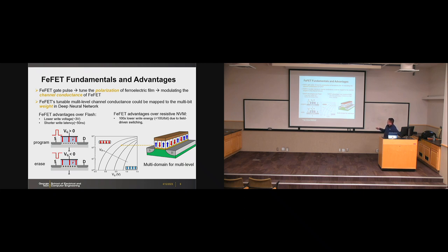So here, if you think about the implementations of the FeFET, we will have this built-in dipole in the gate stack. Then if you have all the dipoles pointing down, the positive charge will assist the channel inversion for the n-type MOSFET. Therefore, here the threshold voltage will be lower if you program the FeFET state to be pointing down. And if you reverse the gate voltage, then you can polarize up all the dipoles, and then you can assist the channel accumulation. So basically, this gate stack will induce or suppress the channel formation. That could be translated as a different threshold voltage depending on the orientation of the dipoles. Because as grown, the ferroelectric thin film may have many domains or grains.